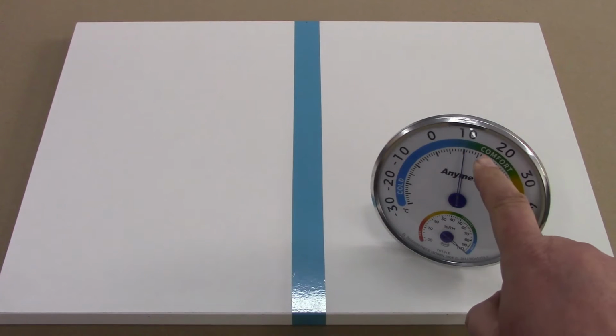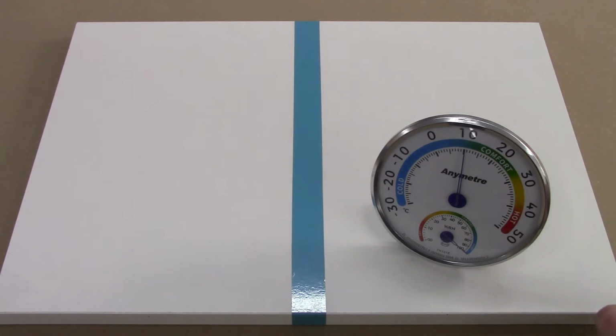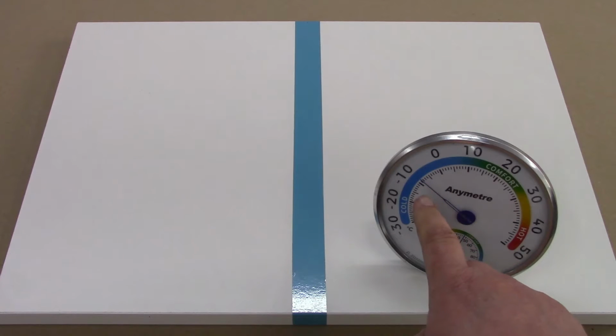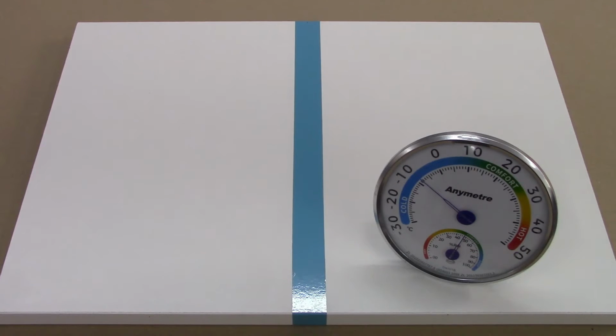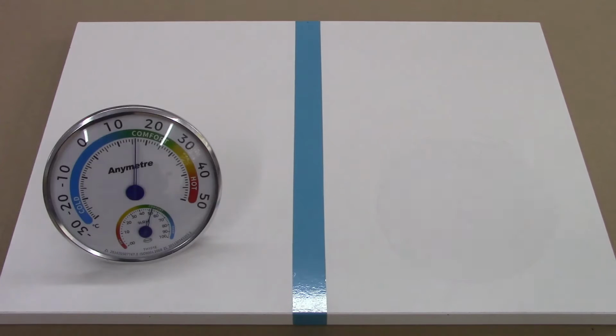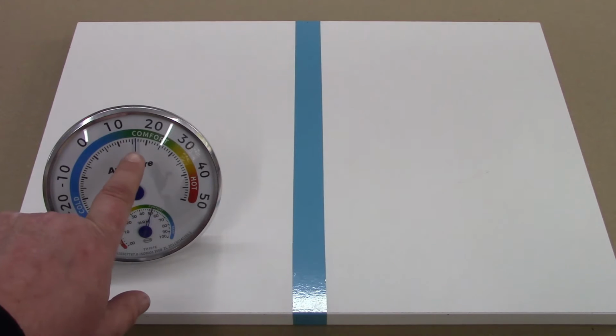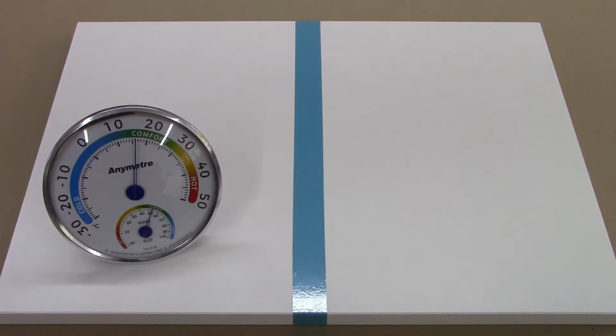Firstly, make sure you have a good workshop temperature. Ideally, you shouldn't be working below 10 degrees C, and certainly not in freezing temperatures. The ideal temperature to use this material is around 15 to 20 degrees C.